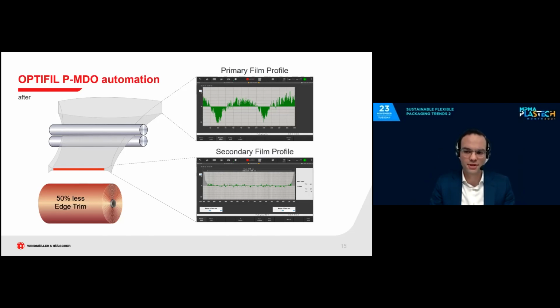So the film entering the MDO unit is not a perfectly flat film like in the slide before. It's a warped film with thin edges. The stretching process smoothes out the film so that you achieve a great profile with much smaller amounts of film that you have to cut away. The edge buildup cannot be eliminated completely. This is physics, but you can reduce the amount that needs to be cut away by about 50%.